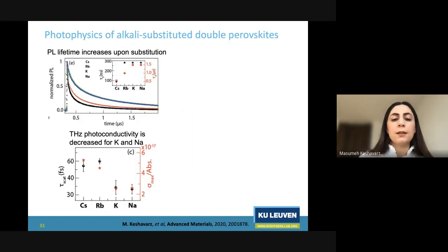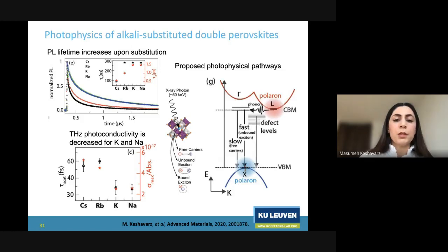And for each lifetime, we can identify where it is originating from, from which wavelength or which energy it originates. First of all, I must say that the longest lifetime, which is attributed to the free carrier recombination lifetime, was 3 times longer for the substituted materials, which can explain the X-ray response for the rubidium, for example. However, the mobility was reduced for the potassium and sodium, but for the rubidium, the mobility was constant, same as cesium, which was measured through time domain terahertz measurements.